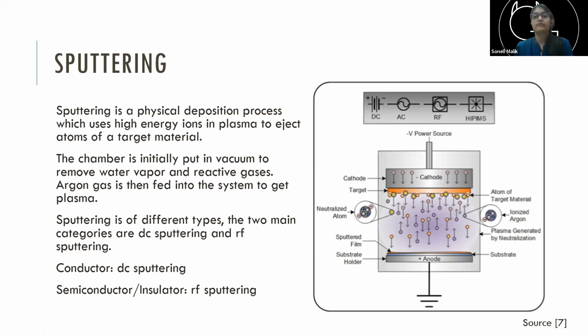Also for RF sputtering, you need impedance matching. Some of you might know that when you want to transport RF voltage across a set of coaxial cables, the load at the end of your coaxial cable needs to be matched to the impedance of your coaxial cable. So that also needs to be accommodated for RF sputtering, which is why for RF sputtering you also need a much higher voltage than you need for DC sputtering for the same rates of deposition. Do you guys have any questions about this?